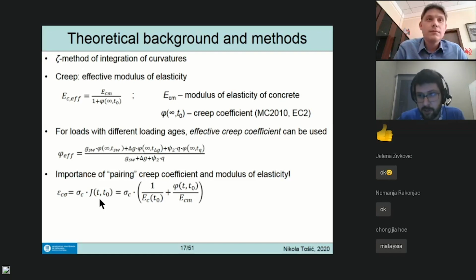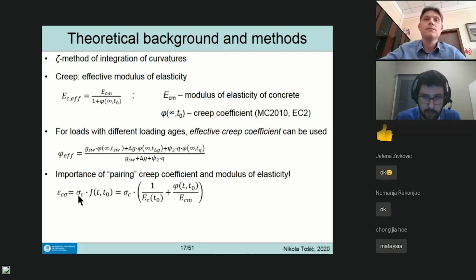So for a constant stress block, the evolution of the stress-dependent strain is linearly dependent on your stress, for what we call linear creep, and this is for loads up to, let's say, 40% of the compressive strength. The strain response is linearly proportional to stress, and this proportionality is expressed through the so-called compliance, which has two factors, and these can look different.